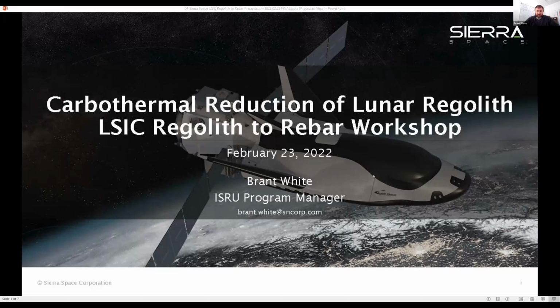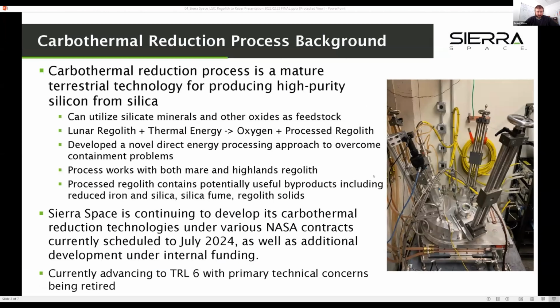So yeah, I'm Brant White with Sierra Space. Just to give you a real quick overview on carbothermal for those of you who aren't aware of it. In a nutshell, it's a mature industrial process to make high purity silicon on Earth, and we've leveraged it to extract oxygen from lunar regolith. The nice thing is it works with both the Mare and the Highland simulant, but at a very high level, we just take the lunar regolith in, we heat it up using direct thermal energy. You react it with a carbon carrier, which is recycled in the overall process. So your net output is just oxygen gas and then your processed regolith slag.